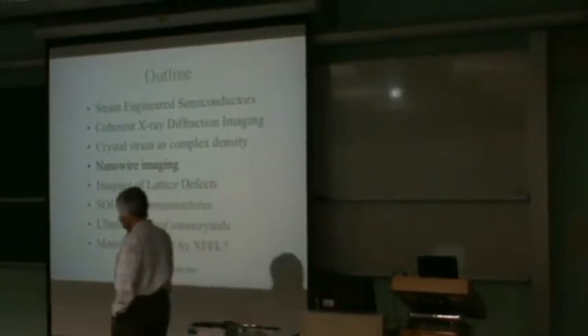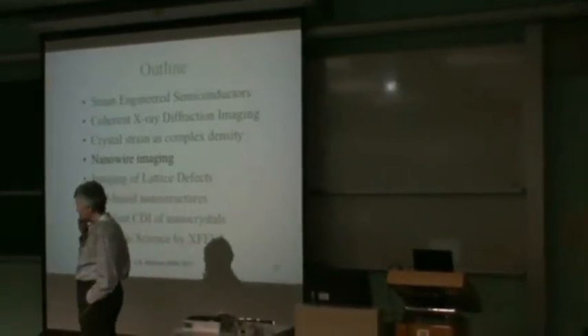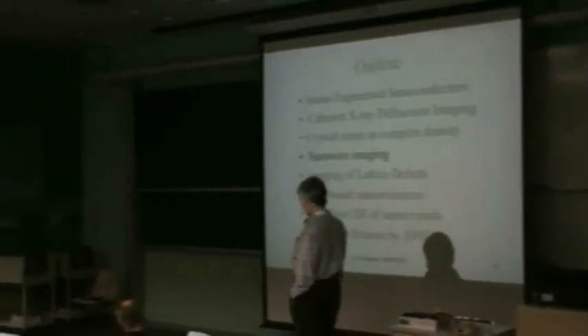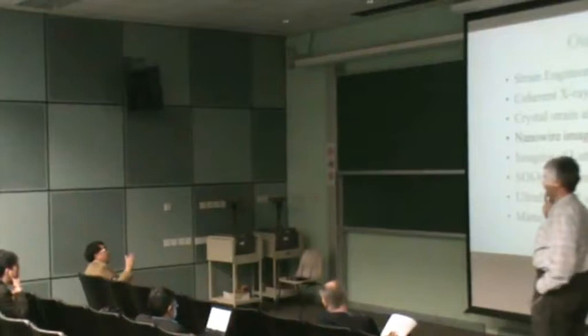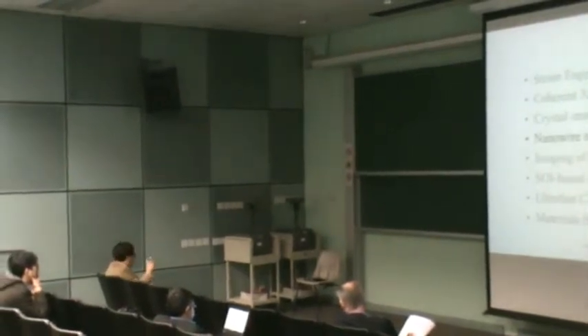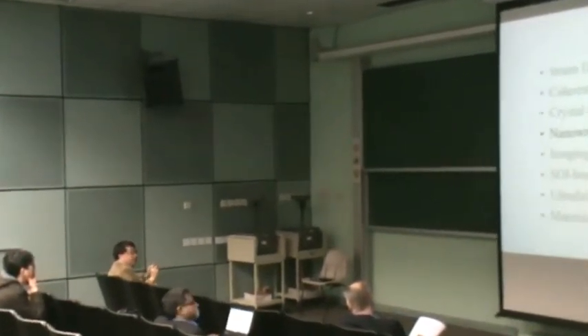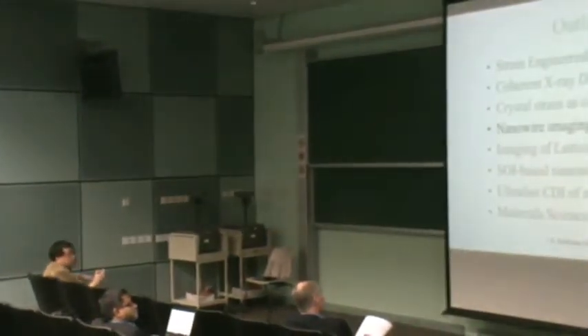At the first part, you talked about this Gibbs-Thompson relation. Yes. Which is the delta P equal to surface tension over R or something like that. Yes. And how did you convert this delta P into your lattice spacing? By the bulk modulus. So the K in that equation was a bulk modulus.